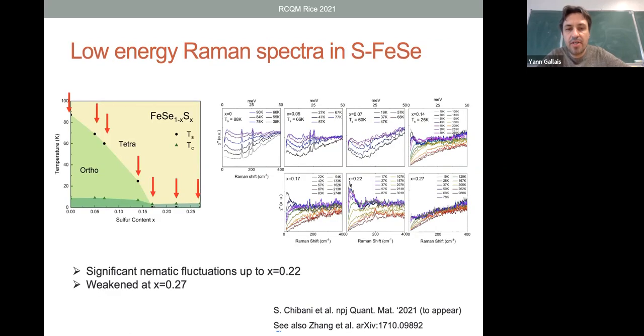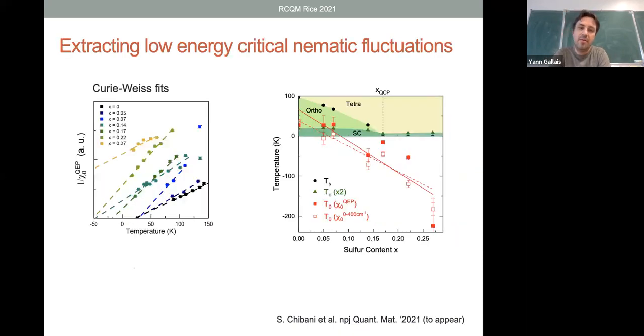So one way to analyze the data is, again, to do the integral of this dynamical spectrum and extract the static susceptibility and fit it with a Curie-Weiss-like behavior, and that allows us to extract a T-nematic. This can be done in different ways, but here I'm showing you two. One is by fitting the low energy part with a quasi-elastic peak and extracting the susceptibility from it, or a direct integration of the low energy.